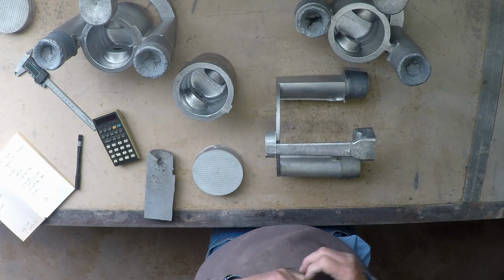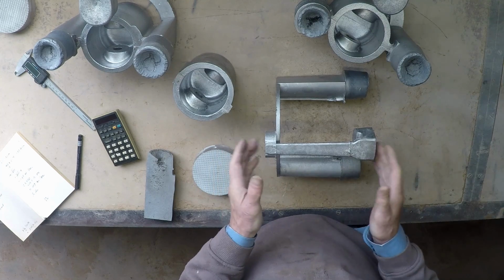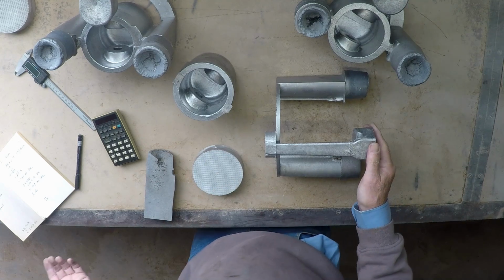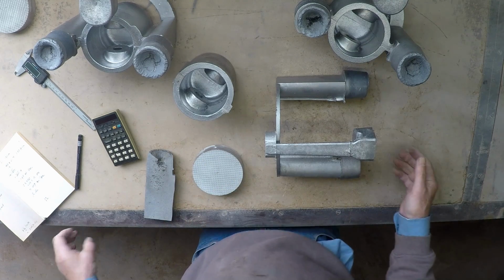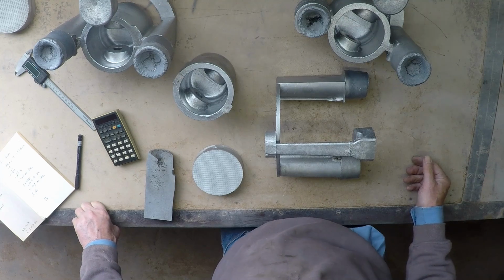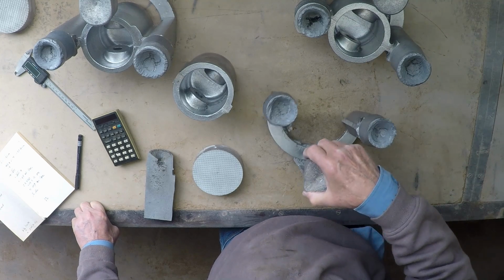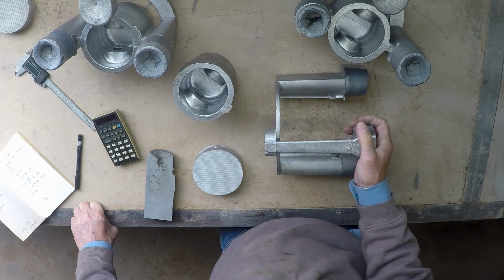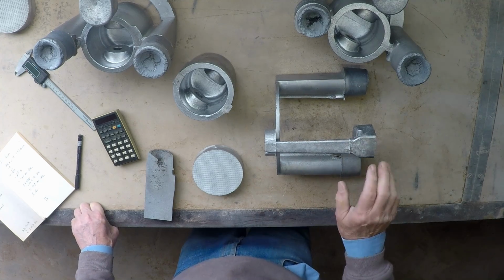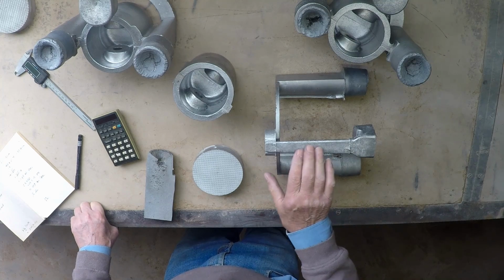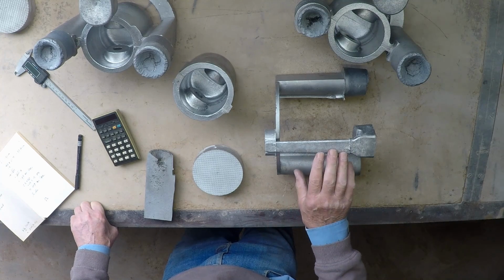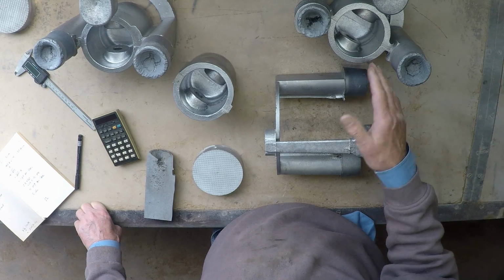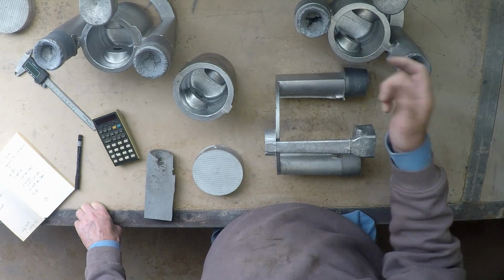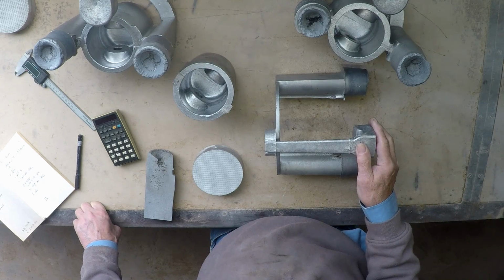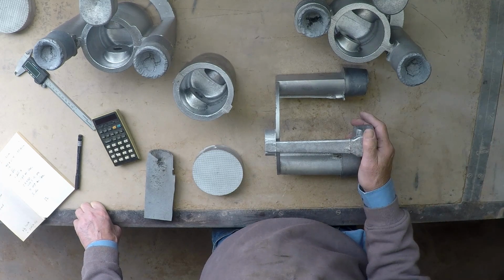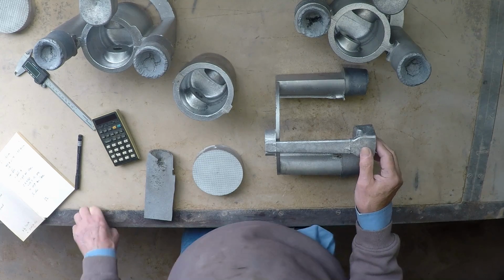So we would get about 300 grams a second from start to finish of the pour, and 300 times 14 seconds comes out almost exactly at what we got, the 4 kilos weight. So that worked quite well, but we feel that was a bit quick, and that we want a flow rate, a fill time more like 20 seconds, because this is a very fluid alloy, and even though it's being poured very cold, it's quite thick, and we figure we can get a slower time. And the old adage of pour as slow as you can is always a good idea.